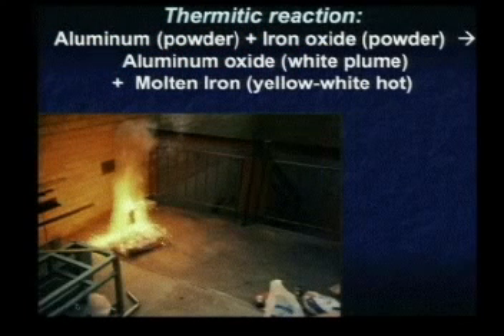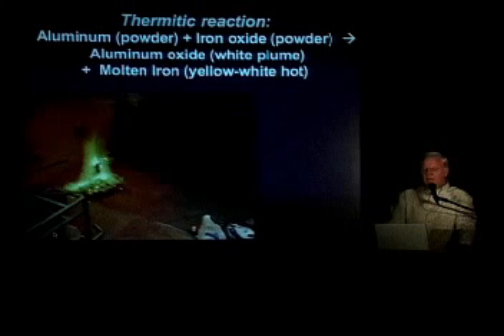The aluminum grabs the oxygen from the iron oxide, and you get the end products, aluminum oxide, much of which comes off in this plume. It looks like smoke, except it's white. It's quite bright, and it floats away, a fine white plume. And the molten iron then forms, reduced iron. We'll see. But I want to just say now, while we're thinking about it, that this red material, when we ignite it, we get iron spheres. Many of these spheres are nearly pure iron. Not enough oxygen in them to be iron oxide, you see.